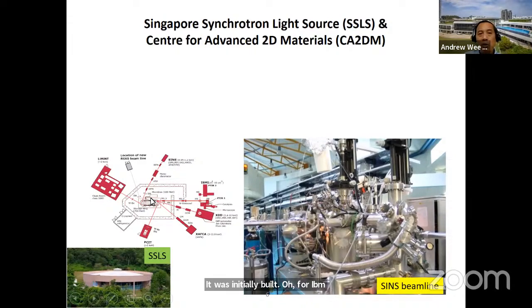It's called Helios 2. It was built for IBM for X-ray lithography, but because that did not take off, it's now used for science. And the beamline that I built up was a soft X-ray beamline, known as the SINS beamline. It's a surface and interface nanostructure science beamline. It gives off photons of the energy range between 50 and 1,200 electron volts. We can do all sorts of spectroscopy on it, RPS, XPS, UPS, and we can do X-ray absorption on it as well. And I'll talk a bit more on XMCD, X-ray magnetic circular dichroism, later on when we talk about magnetic 2D materials.